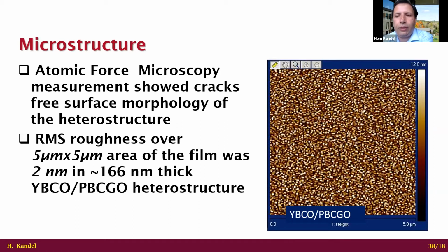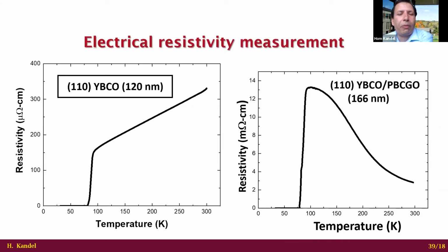The next slide, please. We also perform electrical resistivity measurements. First, there is a 110 YBCO base layer. It is about 120 nanometers, and its Tc0 value is about 82 Kelvin. And on the right-hand side, there is a heterostructure where we have 110 YBCO/PBCGO.